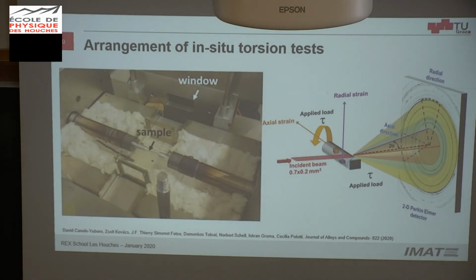We did successfully perform an in-situ torsion test. It took us a while because it was difficult to get the proposal approved. Nobody believed that we could do this, and it took us very long until we could do this experiment. So what is the idea? We do torsion tests, and with this we get an incident beam that we made as flat as possible. So we only probe one part of the sample very close to the surface, and as it rotates, of course, you don't always see the same part of the sample.